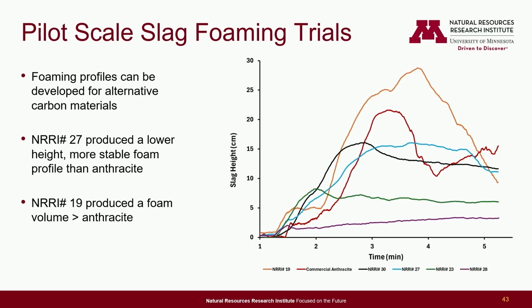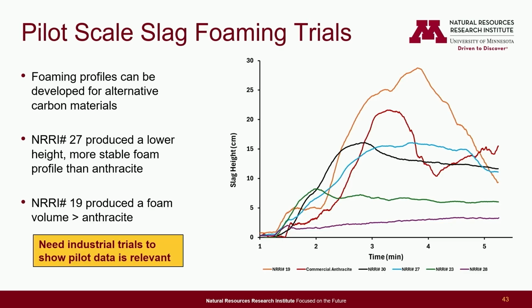And then we have a lot of other formulations that we did. This orange line here exceeded the slag foaming height of anthracite. We had some other ones that failed. This black line is similar. So we're seeing promising results with our pyrometallurgical tests. Again, we need industrial trials to prove that these bench to lab scale metallurgical tests actually correlate to what we'd see in industry, but this is promising.